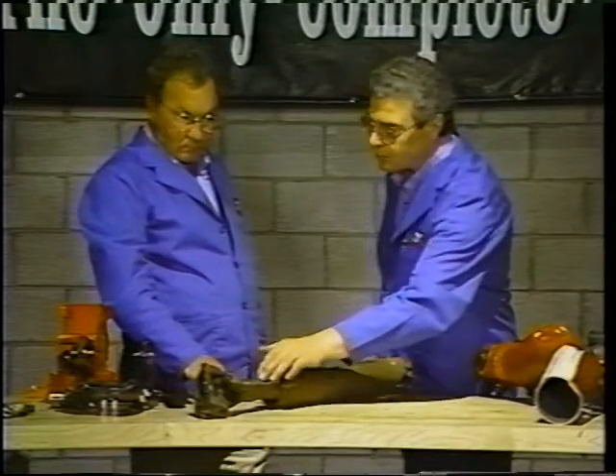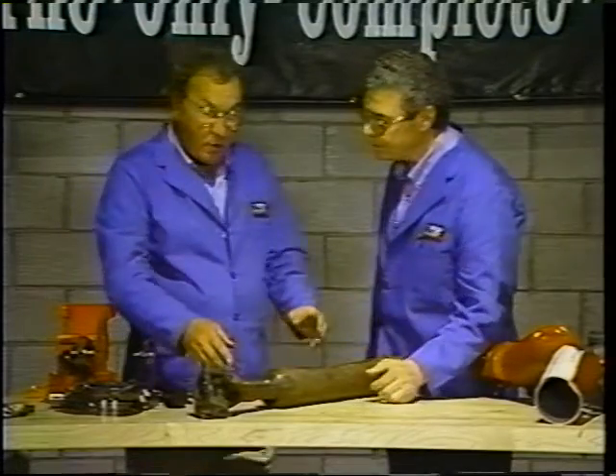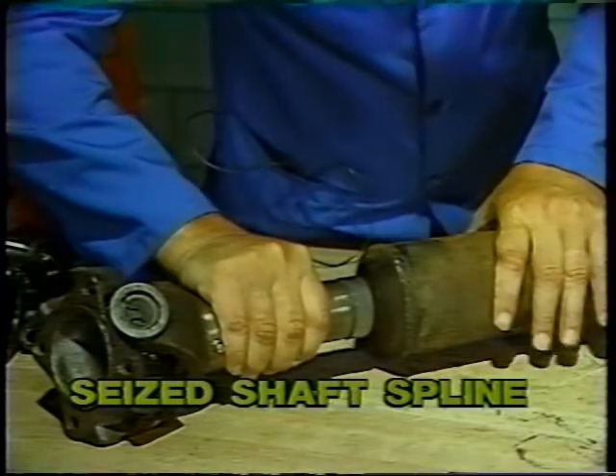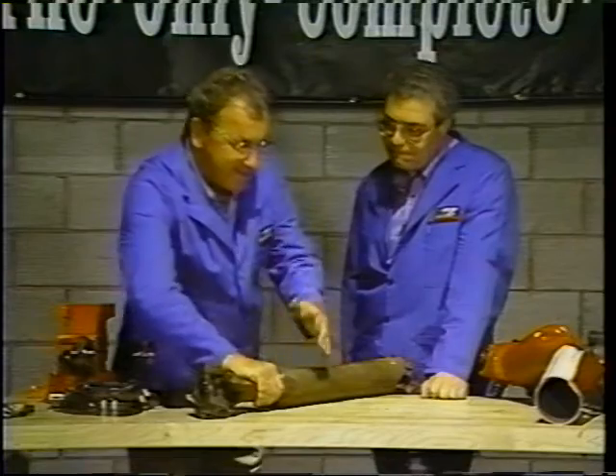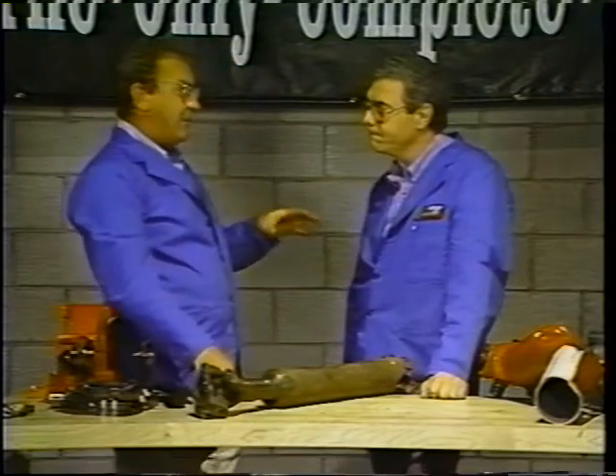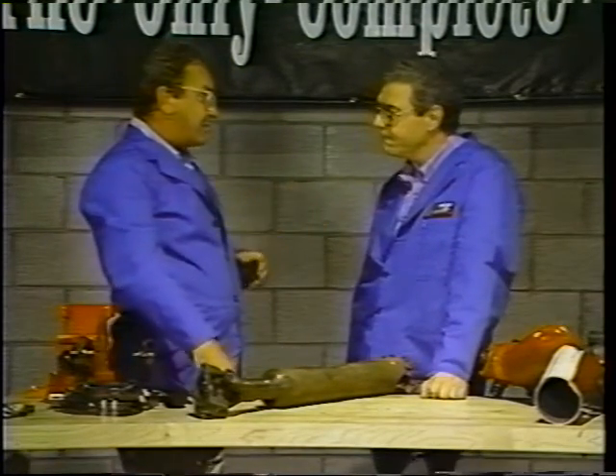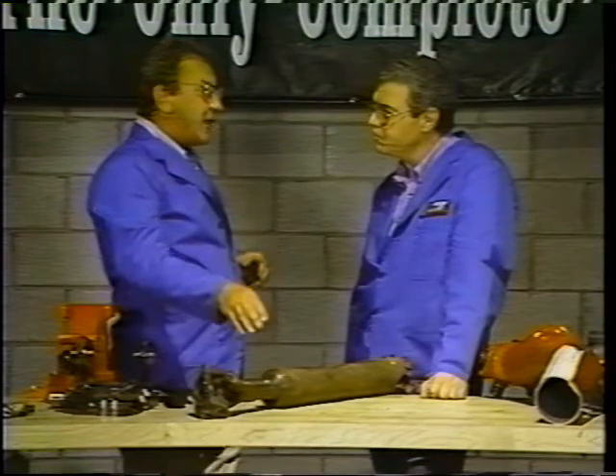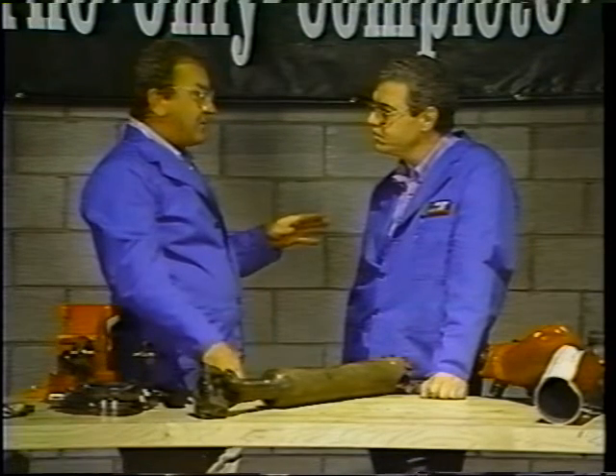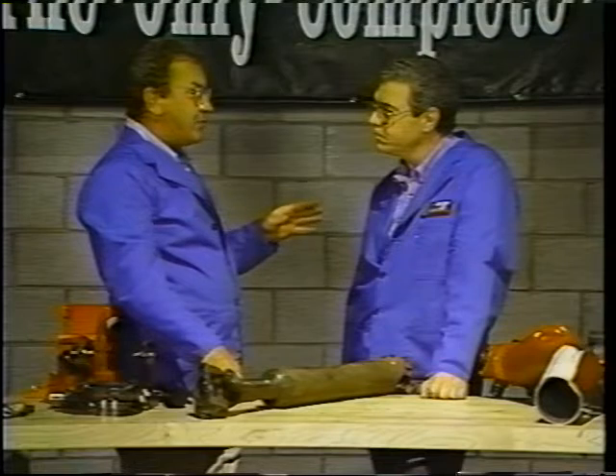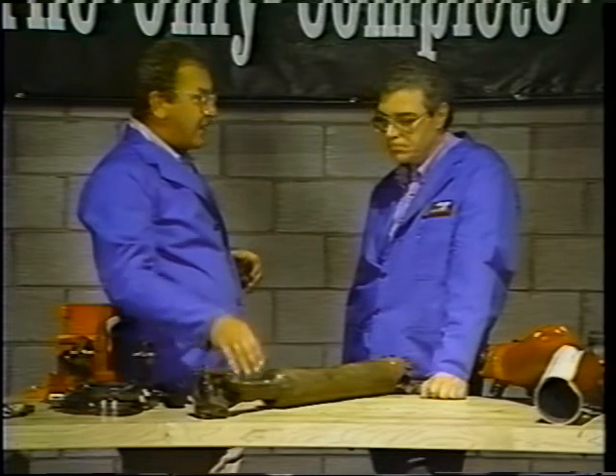Now, here's a shaft spline example. What happened to it? Well, what we see here is a shaft spline that's seized. Improper lube procedures, particularly in the area of lube cycles, lead to this kind of problem. Now, this spline was not glide coated. Spicer's glide coat is a specialized coating that's applied to the tooth shaft spline to help prevent seizures like this.